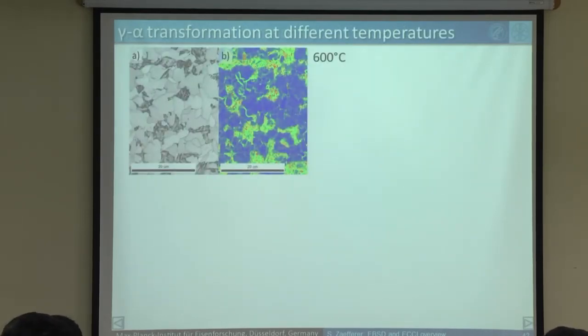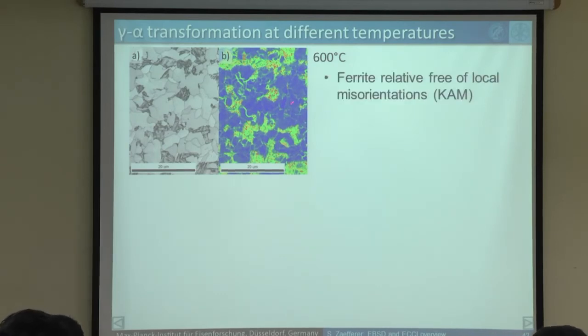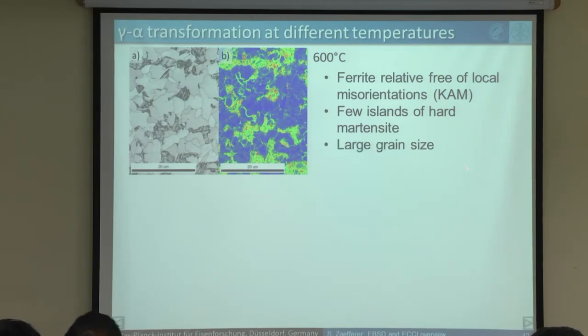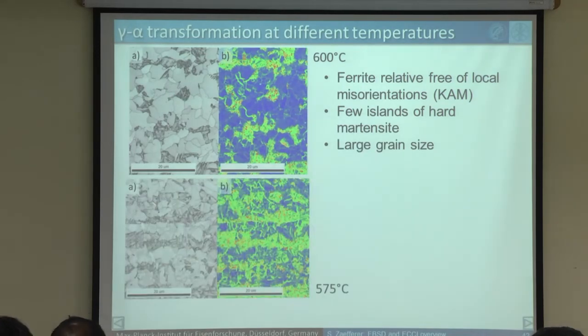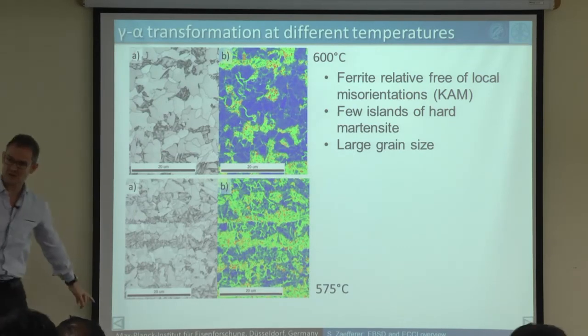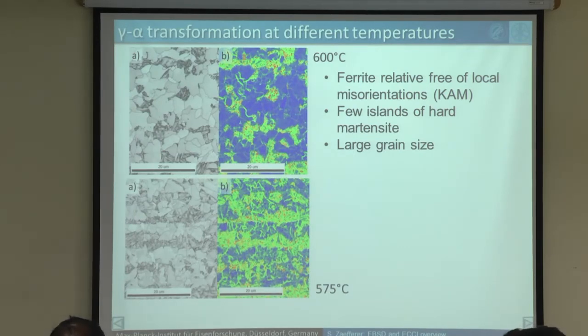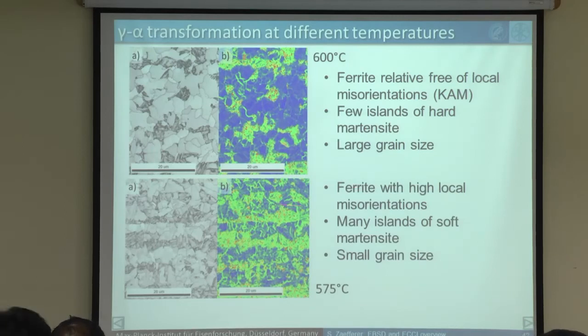So we look into these microstructures. This is 600 degree, and we have relatively large ferrite grains, free of local misorientations. So this is a KAM map. We have few island grains of martensite, and we have relatively large grains. And now this is just 25 degree colder, completely different looking. We have now ferrite, and the ferrite here has relatively high local misorientations. We see many smaller islands of relatively soft martensite, and we see smaller grain size.